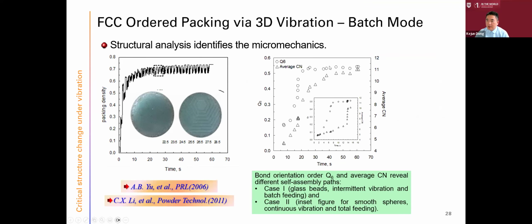So in a previous study, we managed to use the batch feeding and the batch vibration to really transform the random packing into the ordered packing in this way, and reach almost the highest packing fraction of 0.74. And the structure, using the average CN and the Q6, also showed the critical structure change. So at that time, we thought we could only use the batch model to achieve the layer by layer ordered packing, or the transition from disordered packing to ordered packing.